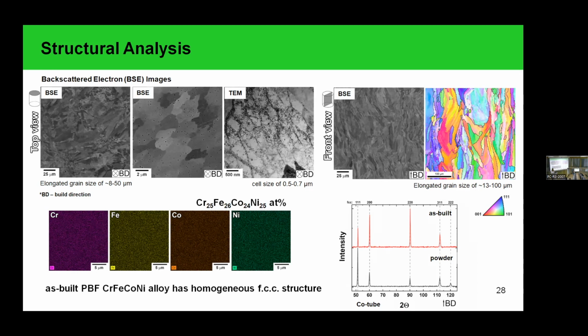In the article it was presented, like the M23C6 carbides in the as-built state. There are small particles about 80 or 90 nanometers in size. But why do you focus on nitrogens only? Because I guess each impurity has its own effect. Because we see the difference in mechanical characteristics only after annealing, and only during annealing we see the formation of these nitrides around the grains. So we assume that it contributes to the mechanical properties of our materials.